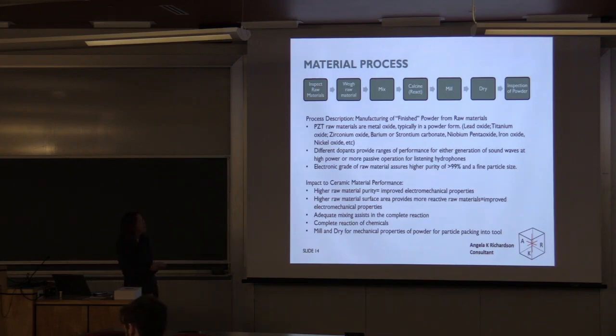From a material process to make the piezo, basically I've outlined 7 different steps here. The first step, inspecting of the raw materials, pretty critical to the quality of the ceramic. So you're starting with metal oxides: lead oxide, titanium oxide, zirconium oxide, barium strontium carbonate, niobium pentoxide, iron oxide, etc. And then, like I said, those different dopants that are going in there provide different electromechanical characteristics. It's usually an electronic grade of raw materials, which means greater than 99% purity and a very fine particle size, usually large surface areas.